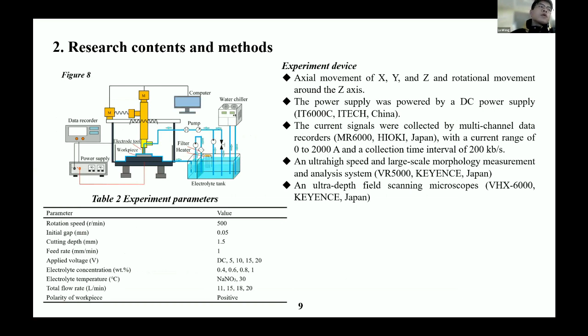The experimental equipment for the study is shown in Figure 8, and the machine device can perform X, Y, and Z axis movement as well as Z axis rotational motion. The power supply was a DC power supply, and the current signal is collected by a multi-channel sampling device. The sampling current range is 0 to 2000 amperes, and the sampling frequency is shown in the figure. The surface morphology of the processed surface after the experiment was measured by a super depth of field microscope and an ultra-high range microscope. The experimental parameters are shown in Table 2.